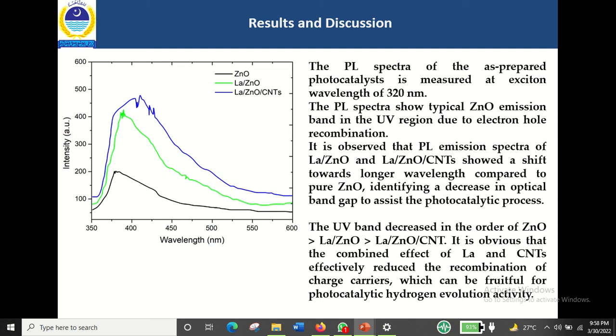The UV band decreased in the order of ZnO, followed by lanthanum ZnO, and lanthanum ZnO CNT shows the lowest UV band as compared to the other samples. It is obvious that the combined effect of lanthanum and carbon nanotubes effectively reduces the recombination of charge carriers, which can be fruitful for the photocatalytic hydrogen evolution activity of the proposed photocatalyst.